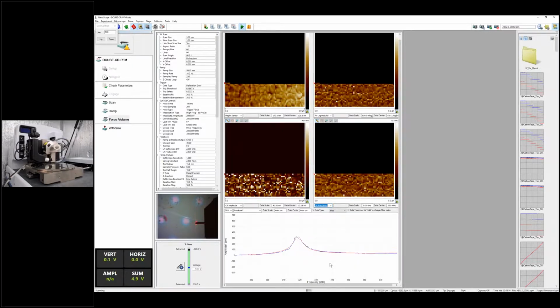So in order to make sure that you always compare apple to apple, you have to make sure that you are really with the same boosting factor, which is actually what we are trying to do here. You always pick up the amplitude at the resonant frequency, so you use the Q factor of your cantilever to boost your piezo response, and that makes it possible to actually compare the piezo response from location to location, from point to point, from grain to grain, from domain to domain. So this is a really apple-to-apple comparison. And that's also an important reason why we set up a separate mode called the DataCube contact resonance PFM.